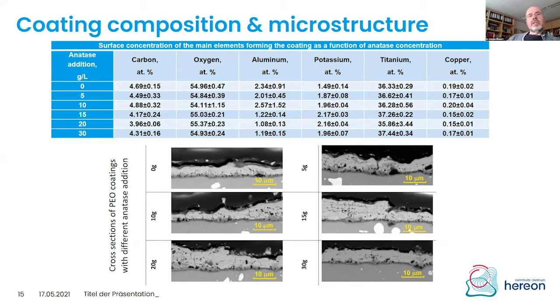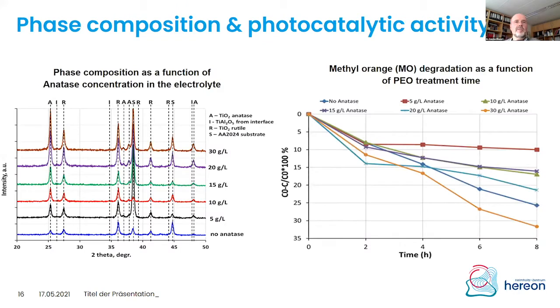But you see on the cross sections, which are shown here for the different amounts of particles added, that the microstructure is definitely not really changing. We still have titanium dioxide on the surface, and then comes this mixed oxide interface layer. And we have checked: we have a relatively stable titanium concentration at the surface, which is not a surprise because it is titanium dioxide. Whether it is rutile or anatase, we don't know. For that purpose, we have done X-ray diffraction again. And if you look at the diffraction diagrams, you see clearly that the anatase share becomes larger and larger when we add anatase particles to the electrolyte, so we can tune the ratio.